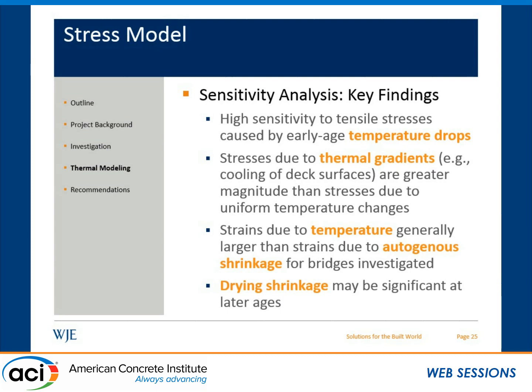We also found that stresses due to thermal gradients, which might occur, for example, by cooling the surface of the bridge deck, were generally greater in magnitude than stresses due to uniform temperature changes. So being able to model those thermal gradients was very important in determining what stresses are more likely in the bridge deck. We also found that the strains due to temperature were generally larger than the strains due to autogenous shrinkage at early ages, because the autogenous shrinkage is a much smaller stress in general. It was about 30 psi at the maximum for most of our simulations.